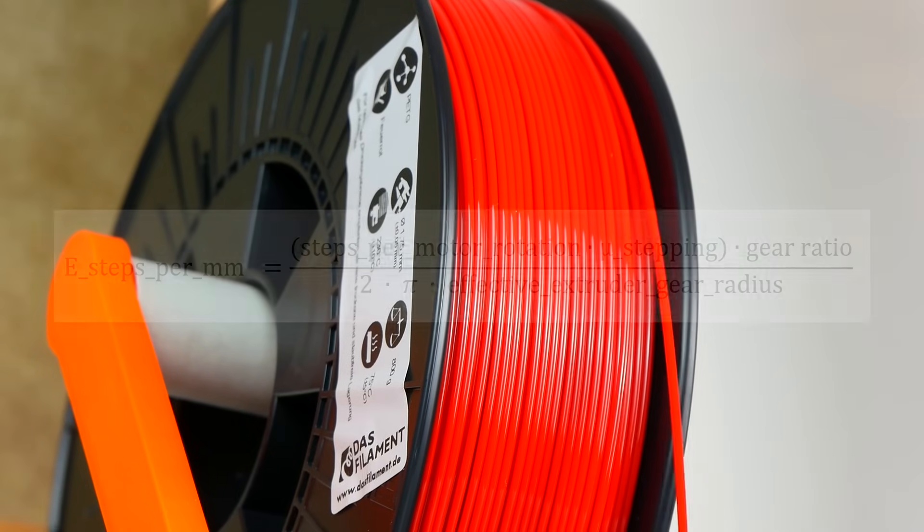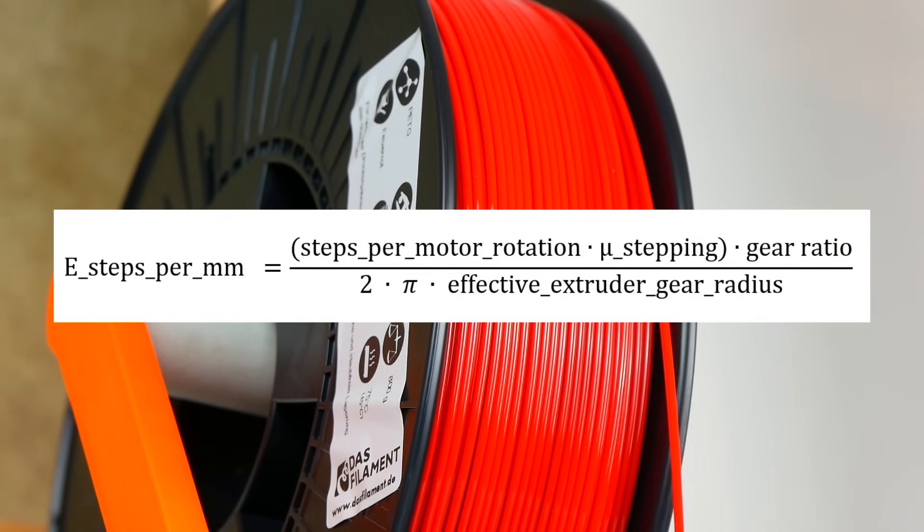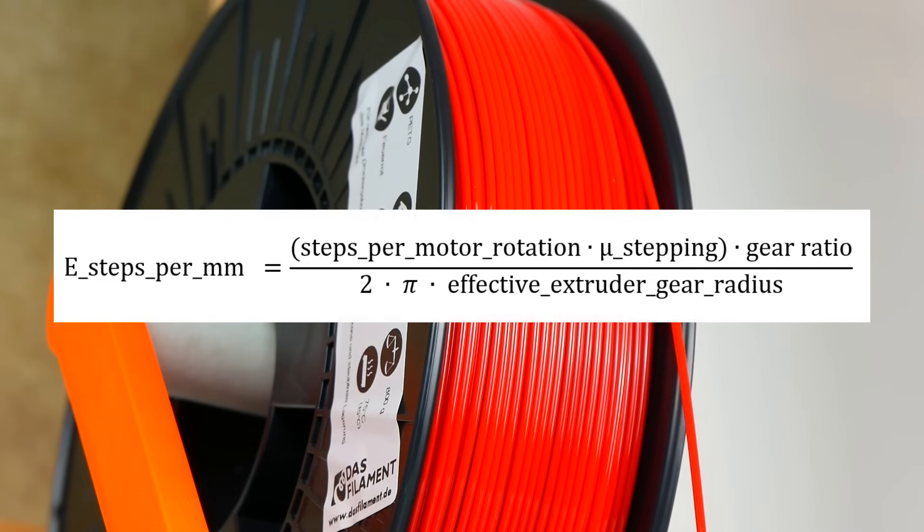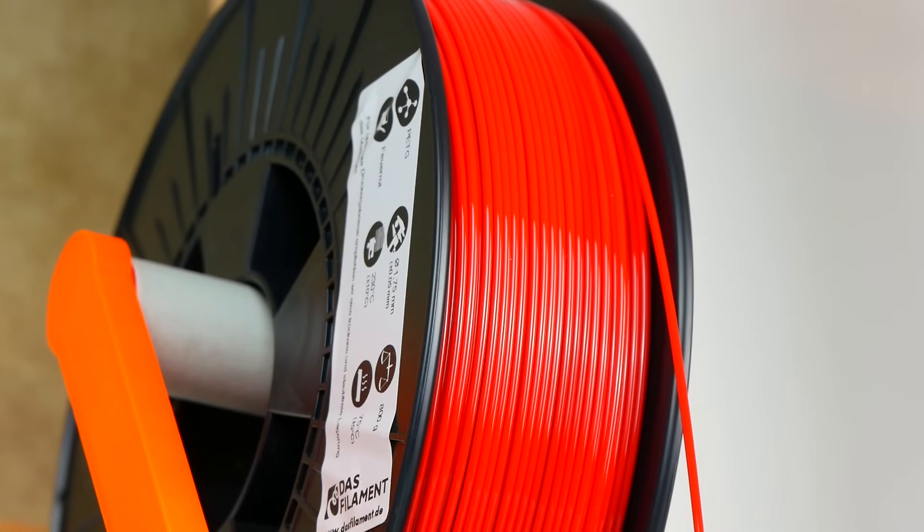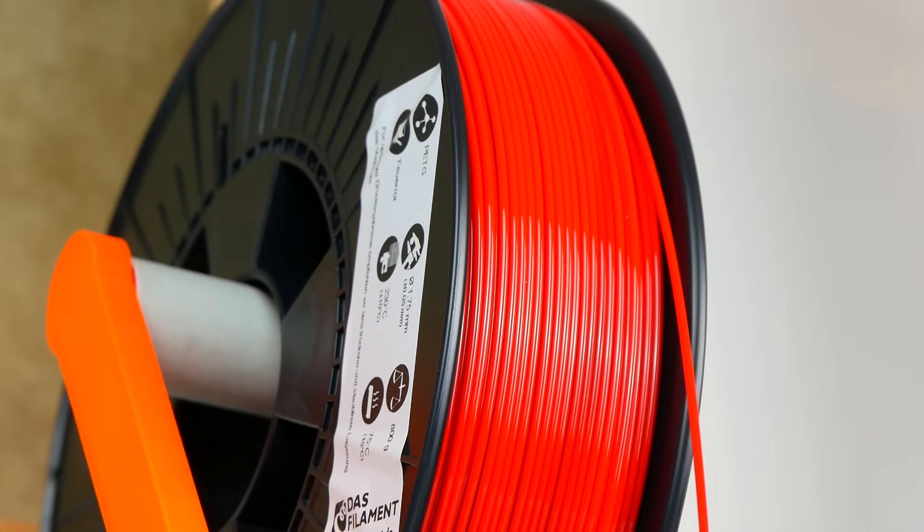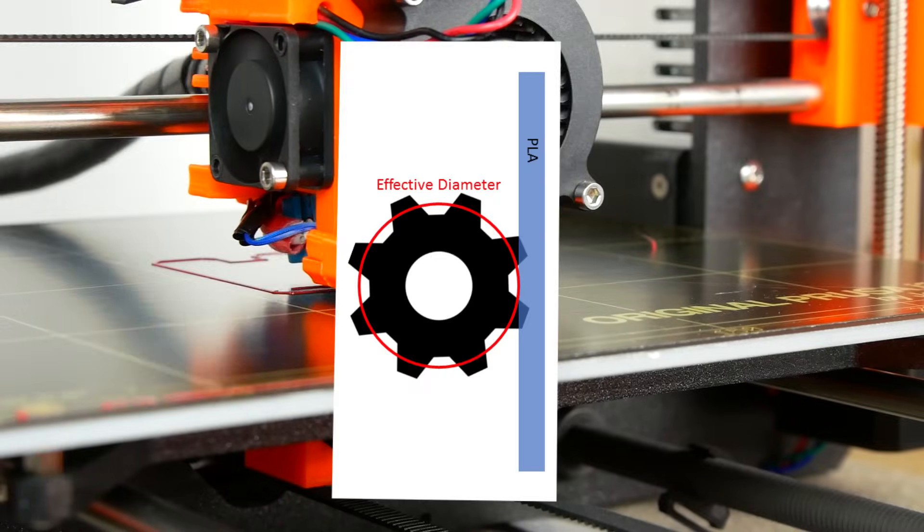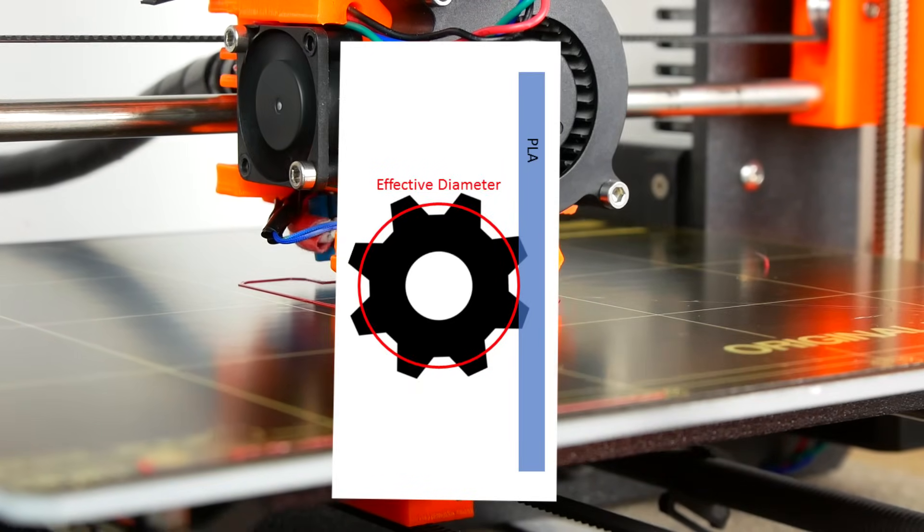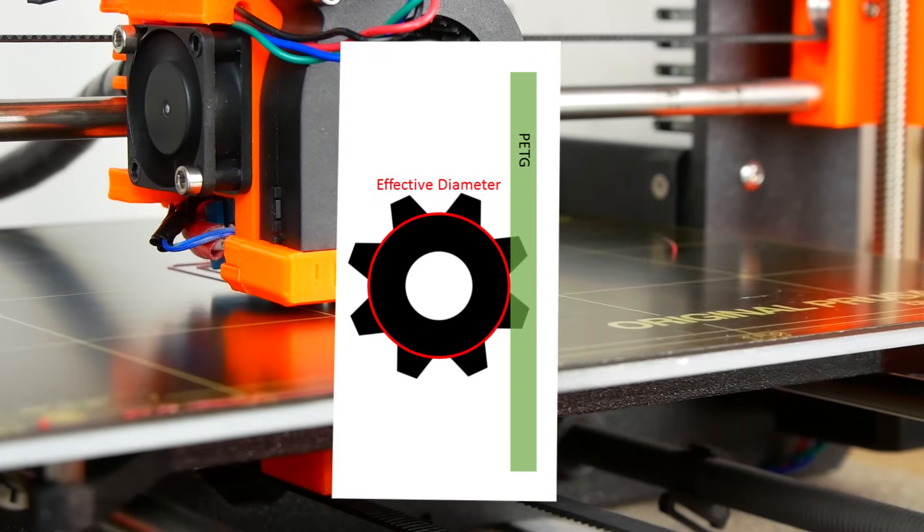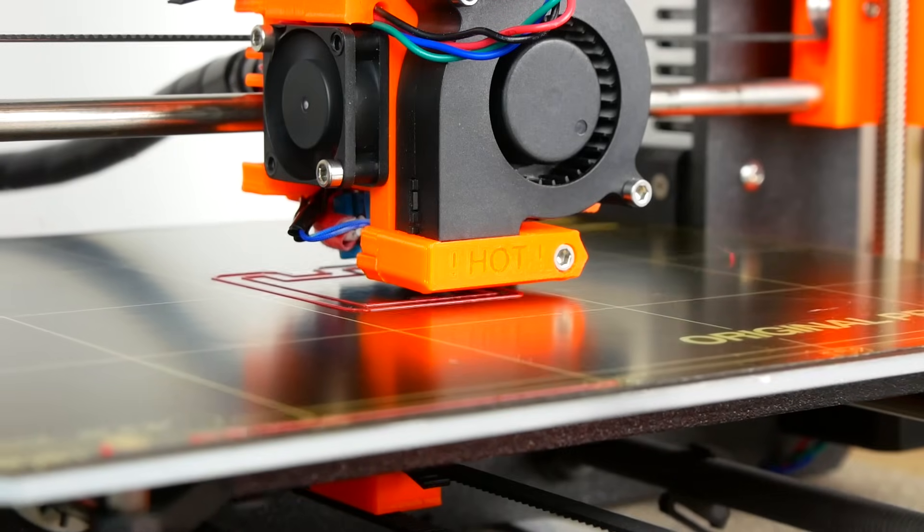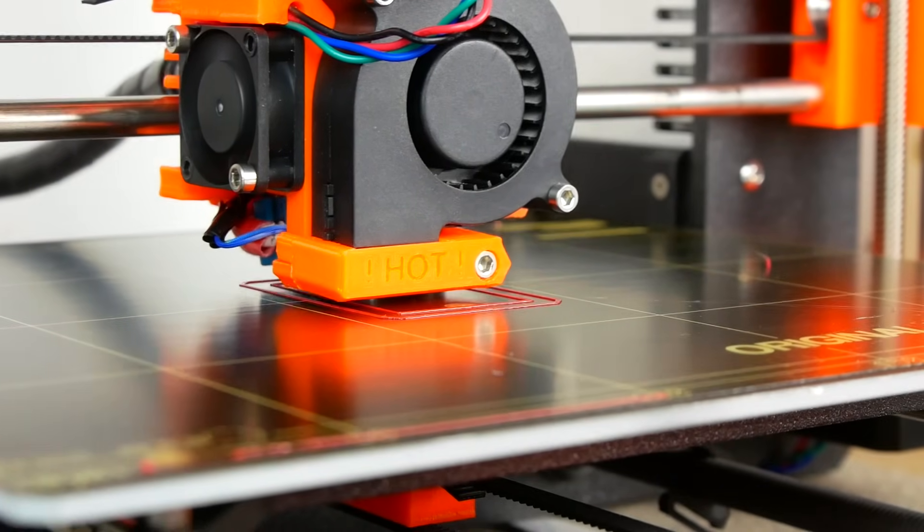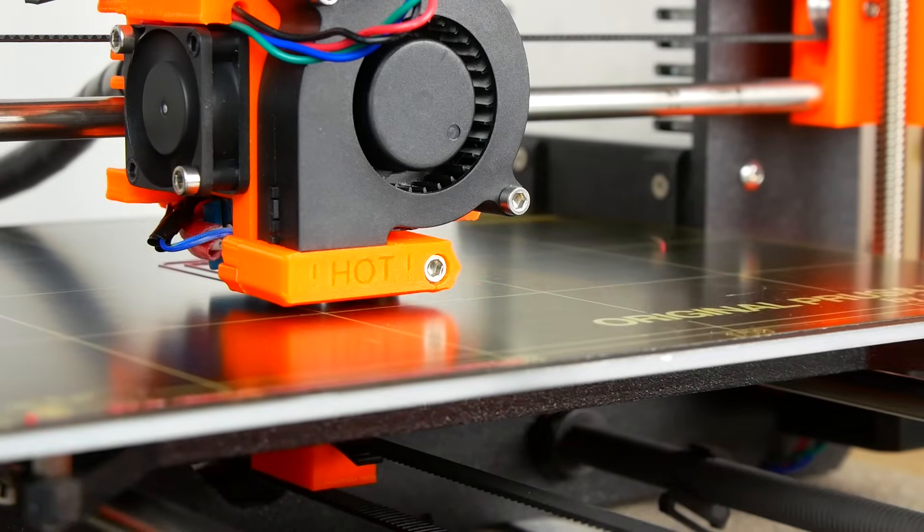You can roughly calculate this value if you know how many steps your motor needs for one rotation of your extruder gear and if you know the radius of your extruder gear. But everyone who already worked with different material groups knows that, for example, PLA and PETG behave differently. PLA is stiffer so it does not get pushed into the teeth profile of the gears as far as PETG. This means that the effective radius is bigger and therefore you need less steps per mm as with PETG. There usually is quite a good value for the calibration factor in your firmware, but I highly recommend to tune it in for each material group separately.